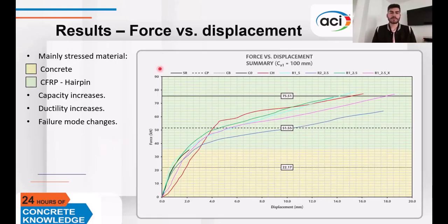This graph summarizes the force versus displacement behavior of most specimens. The black curve represents the unreinforced control specimens. You can see that failure occurs at a higher load than the theoretical one of 22 kilonewton. Then we have reinforced specimens. Clearly, every reinforced specimen surpassed the control capacity, changing the failure mode and achieving a higher ductility as well. You can see the moment the reinforcement starts to work, which is after the initial cracking associated to concrete breakout, and this is evidenced in a change in the slope of the behavior, which is the green zone.